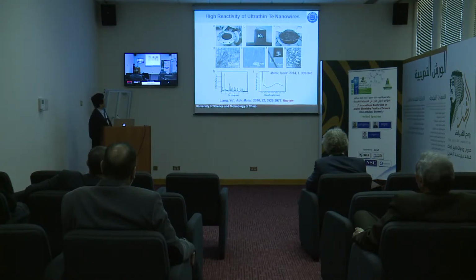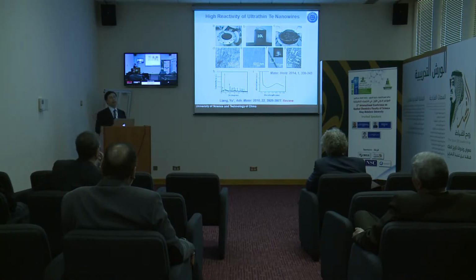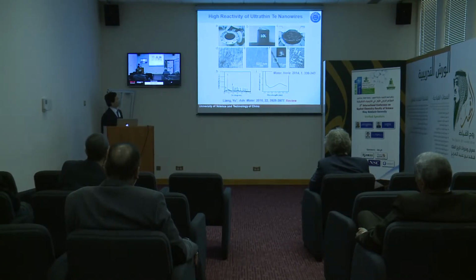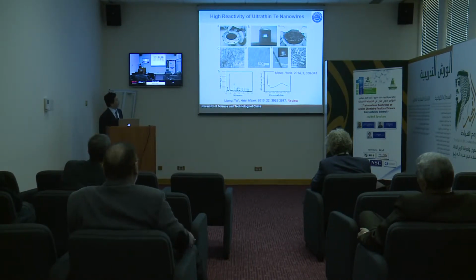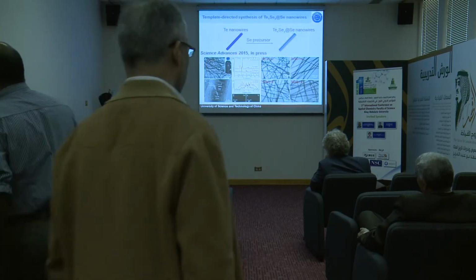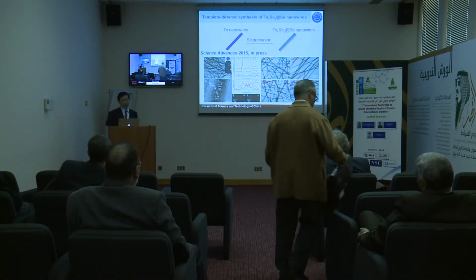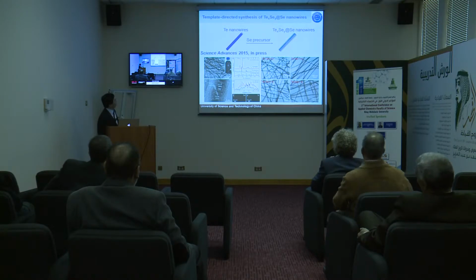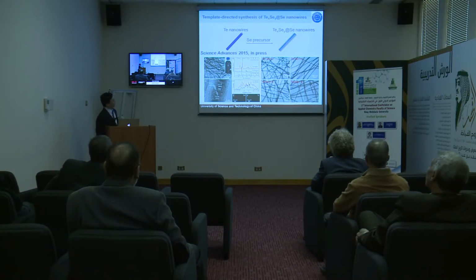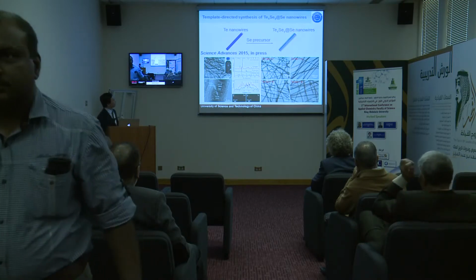Now we can synthesize this ultra-thin tellurium nanowire in huge amount. We can do such a reaction in reactors of 10 liters, so that in one batch of synthesis you can get a kilogram of these high quality nanowires. You will check the morphology of this nanowire. The high quality is really very good. Now if we further coat the tellurium nanowires with selenium, selenium sits in the same group, so that you can get these core shell nanowires.